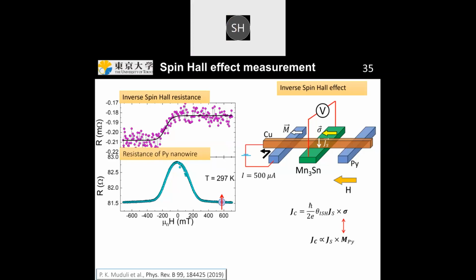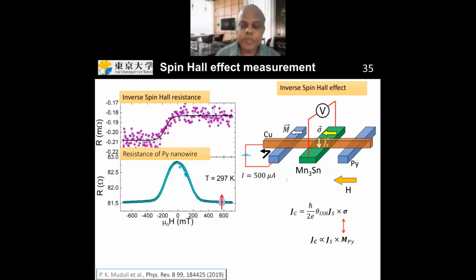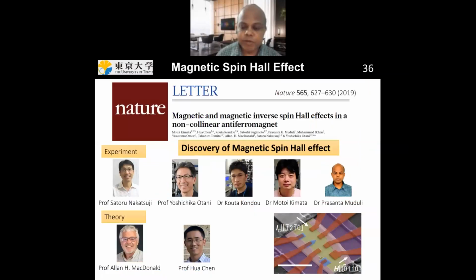It's a good question. The total spin Hall angle will depend on the magnetic spin Hall angle plus your normal ordinary spin charge conversion. If sometimes the magnetic spin Hall effect dominates, then you can have a very large spin Hall angle in certain orientation directions. In the Nature paper we have done an angle dependent study, where we have seen that at 60 degrees with respect to the applied direction, the spin Hall angle is maximized. Yeah, that's what I was asking. Okay, thank you. Yes, I will see that.